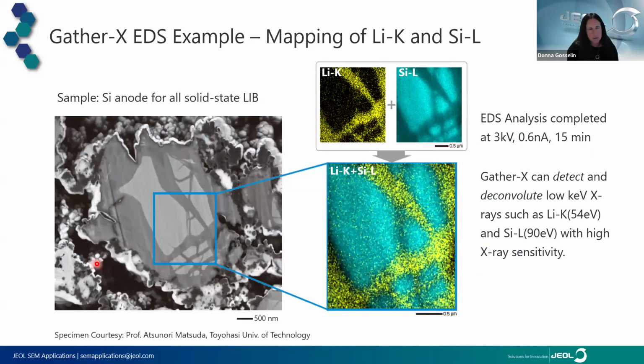And here's an example of map data collected with our GatherX. This was a cross-section of a silicon anode of an all-solid state lithium-ion battery material. And we can see the X-ray intensity maps, the lithium in yellow, the silicon in cyan, and we can detect and deconvolute these low energy X-ray lines with very good resolution. And it's pretty amazing since the silicon L and the lithium K lines are only about 36 eV apart.